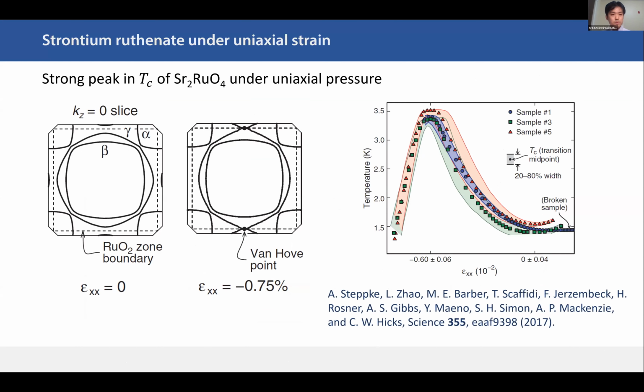So let me first focus on strontium ruthenate that many speakers talked about in this session. This is one experiment under uniaxial strain on this strontium ruthenate, where by applying a strain, we see a touching of the Fermi surface at the zone boundary. And corresponding to that, they also observed the enhancement of Tc to superconductivity, which is shown here.